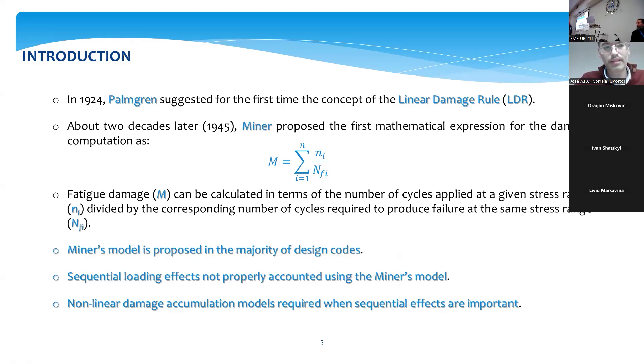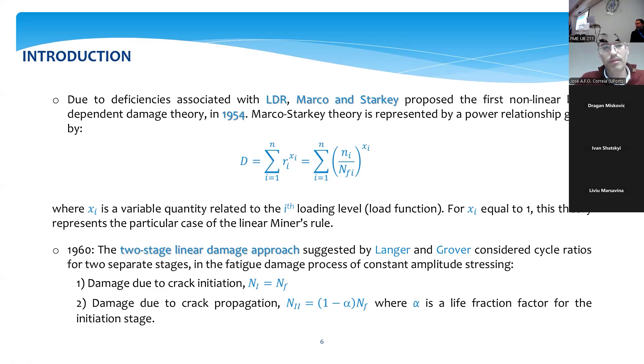We know that the sequential loading effects are not properly accounted for using linear models, and non-linear damage accumulation models are required when sequential effects are important. We know that any detail is subject to variable amplitude loadings, and a lot of codes were developed from Palmgren. The first attempt to consider non-linear loading effects was proposed by Marco and Starkey with an exponent that tries to consider the variable quantity.